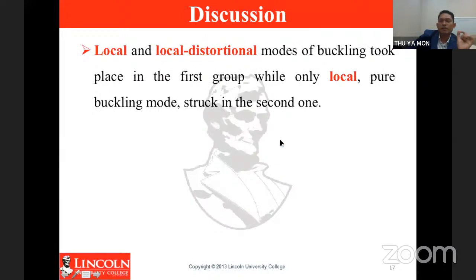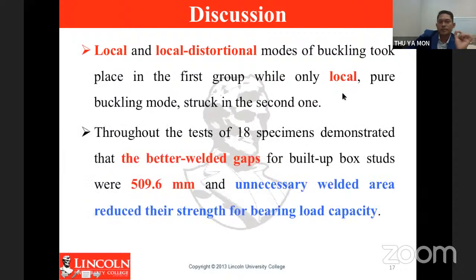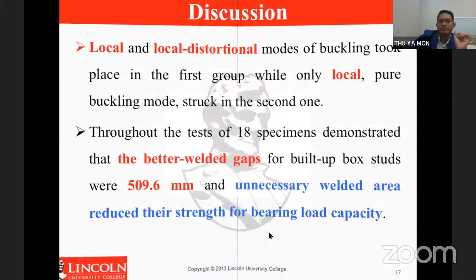Also for the mode of buckling, in the first group, group A, we can see two types of buckling mode: the pure local buckling mode and the interactive local-distortional buckling mode. But in group B, the second group, we can see only the pure local buckling mode. So this experiment demonstrates that the best weld spacing for the built-up box is 509.6 millimeter, and it is recommended that unnecessary welded areas be avoided since they reduce the strength for bearing load capacity.